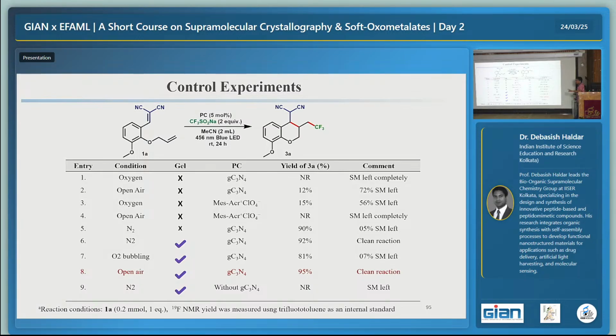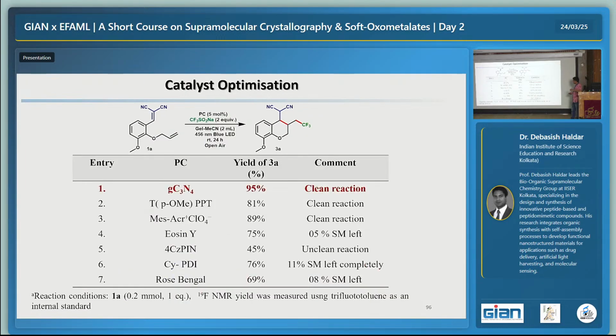If we compare the previous one and this one, in the previous one a 2D molecule has converted to a 3D molecule, and due to this size exclusion it ruptured the gel fiber and the gel melted to solution state, and then oxygen intervened and stopped the reaction. But here there is no such three-dimensional molecule, so the gel fiber is intact, and so we are getting reaction with 95% conversion.